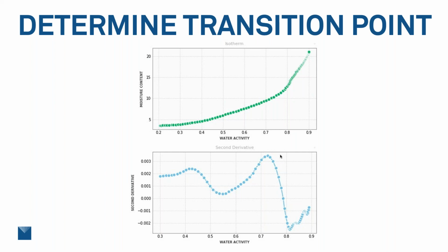The water activity of this granola bar natively is about 0.2. So as we're moving up and increasing in water activity, we want to know, when is it first going to hit that transition? So I want to use the first transition, and the first transition is right there at 0.42 water activity. So that's the one I'm going to be using in my calculations. I'm not going to use the bigger one, because by the time we get there, it's already had a change.